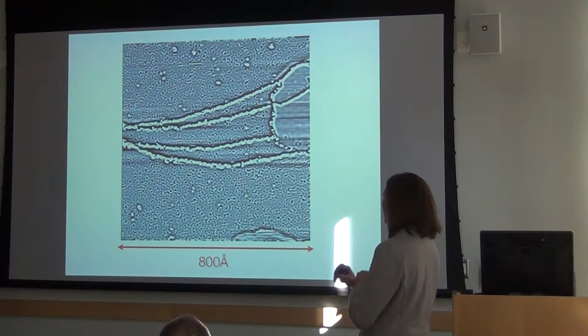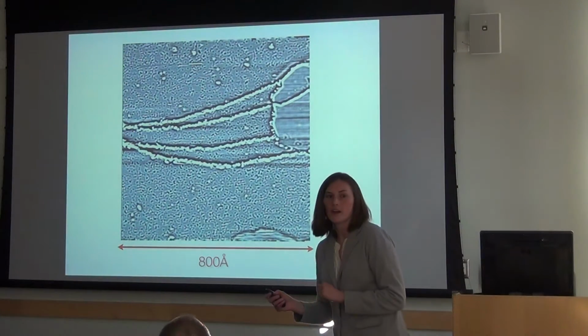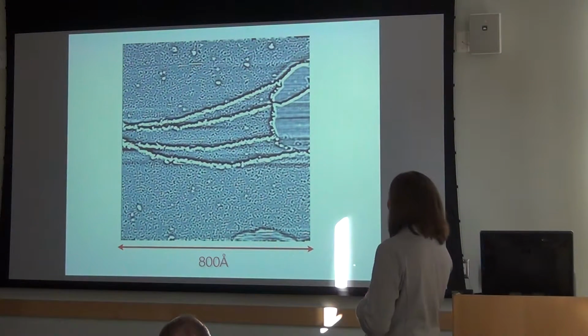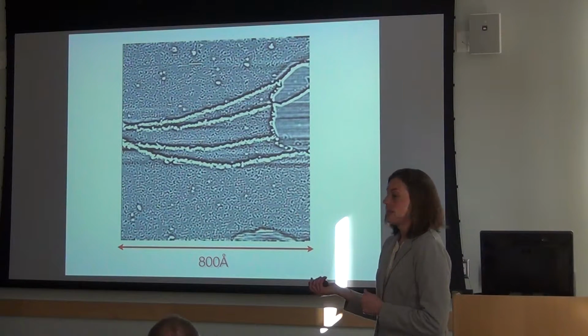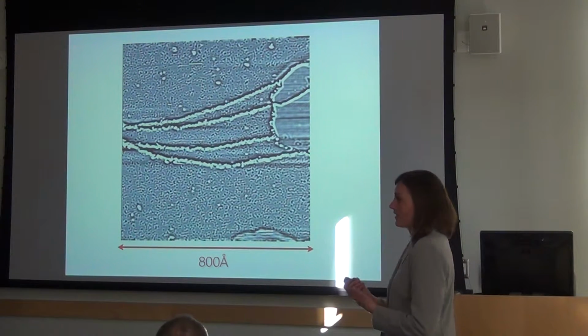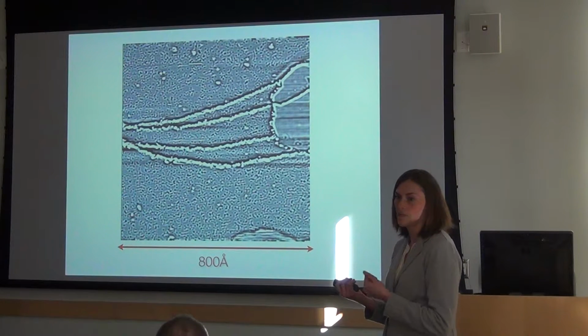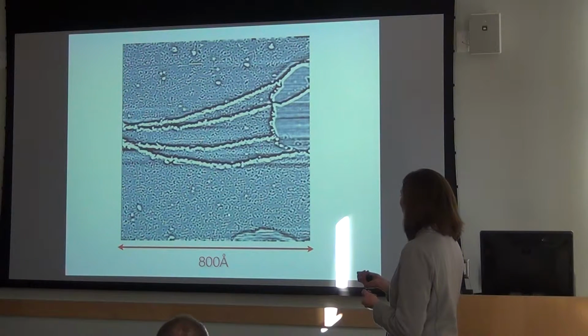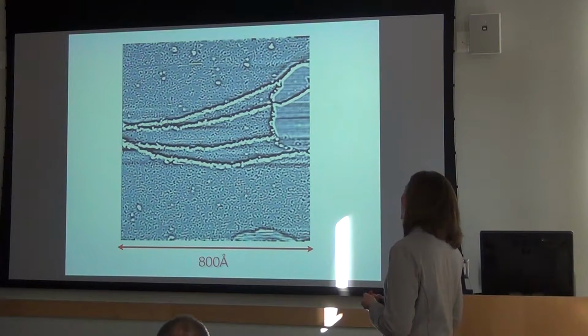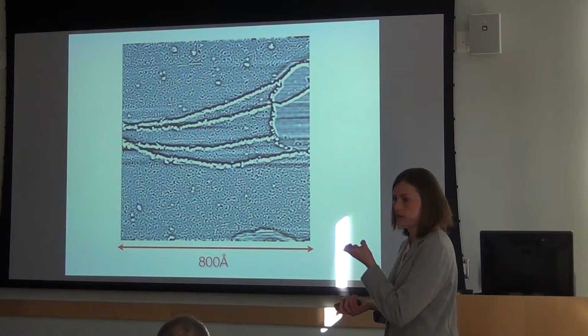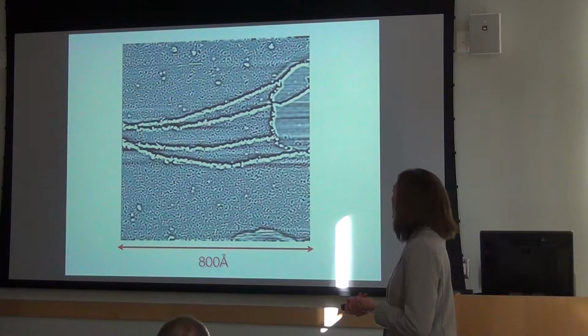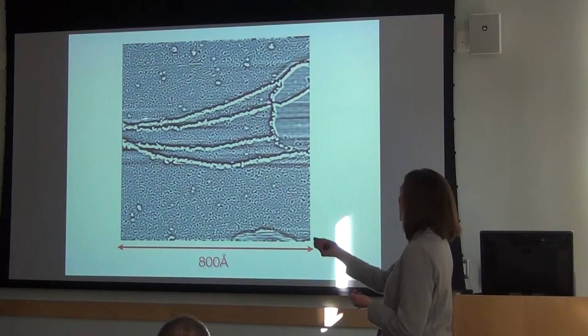Okay, so this is the tour of the experimental system. This is an 800 angstrom wide image of graphene. So graphene are these nice smooth-looking areas on copper 1-0-0. And this is what I meant by UHV. It's still not perfectly clean. All of these black dots here are defects on the surface of the copper lattice. And these are step edges here.